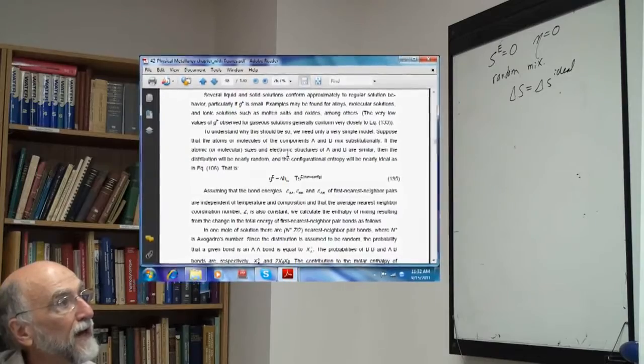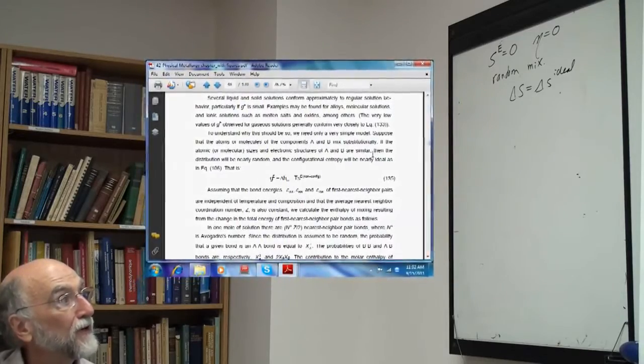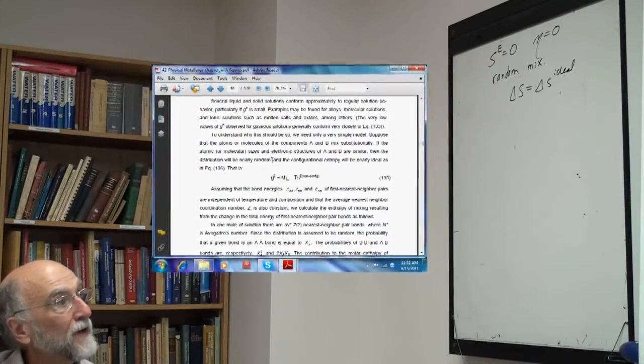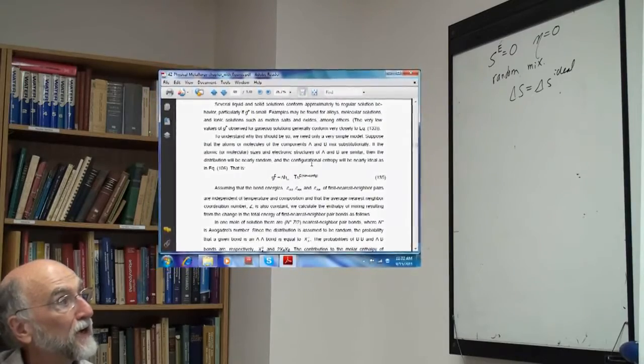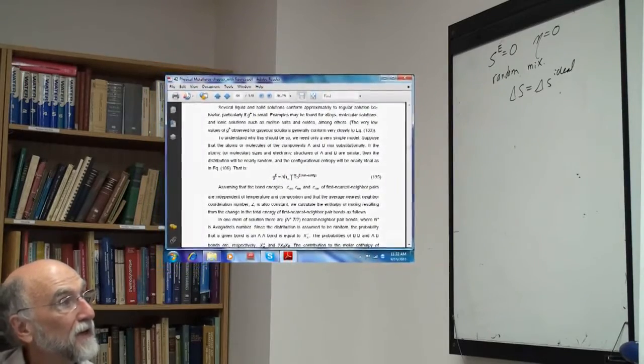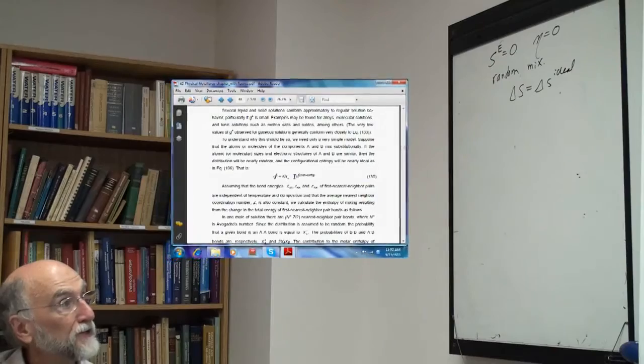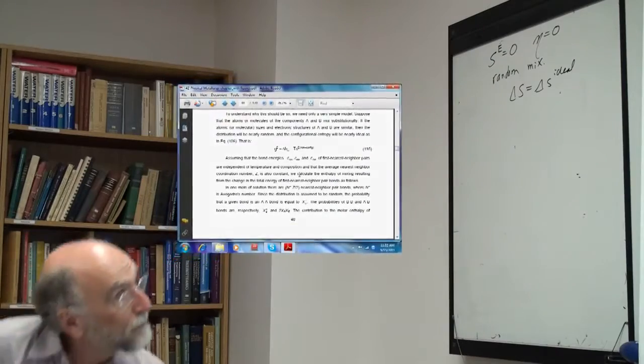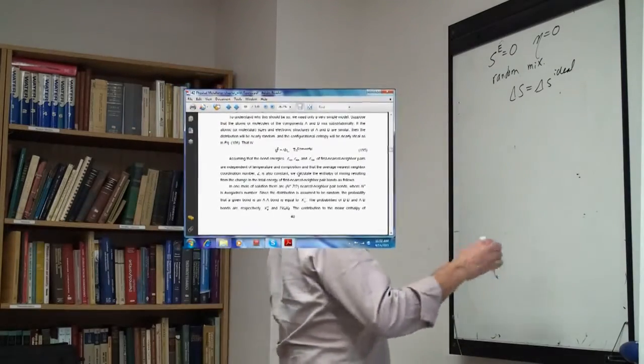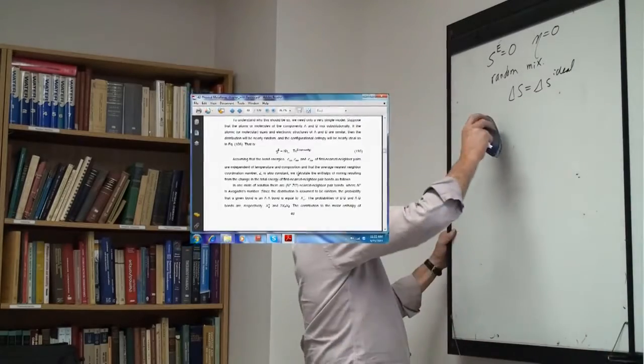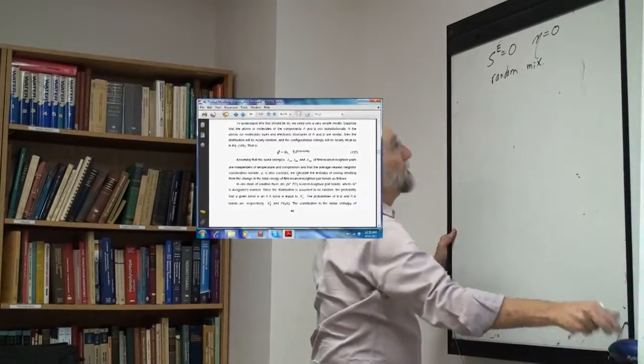Okay, suppose that the atoms' electronic structures of A and B are similar, then the distribution will be nearly random, and the configurational entropy will be nearly ideal. So the excess Gibbs energy is equal to delta H mixing minus T S^XS non-configurational. So we assume a random mix. We're assuming a random mixture.